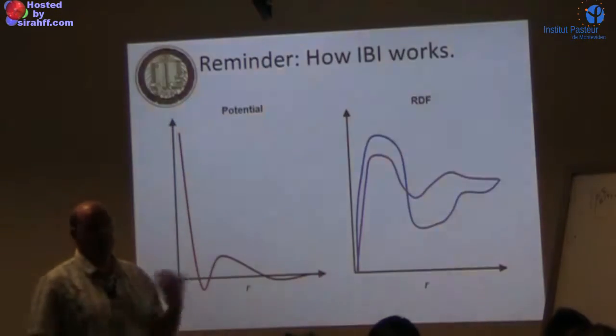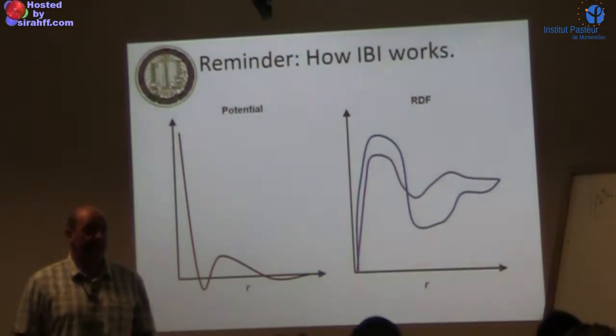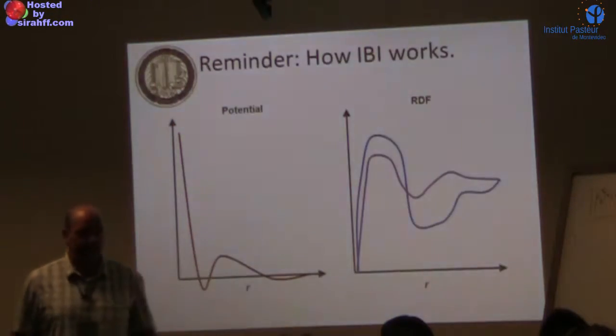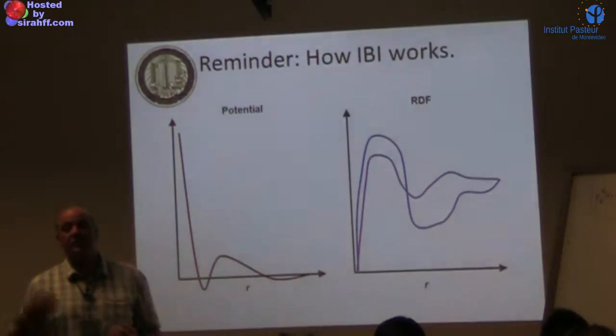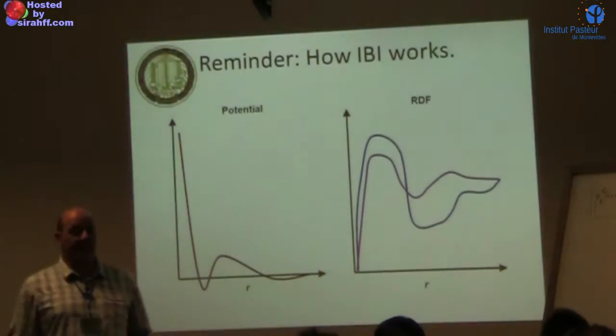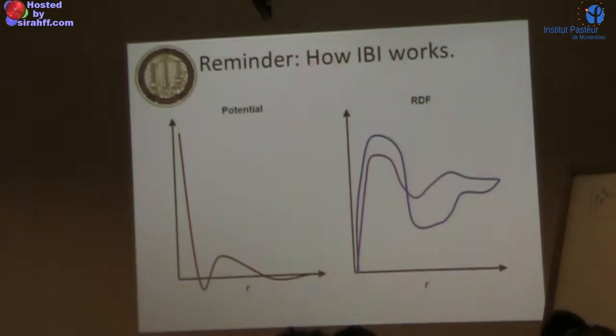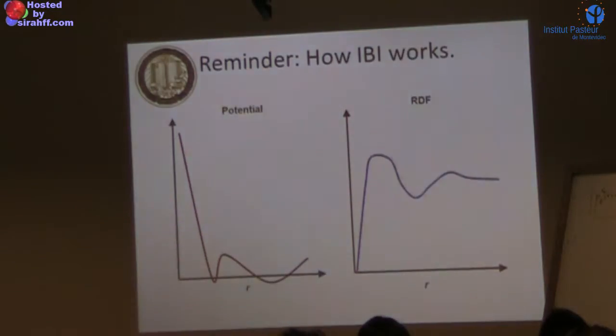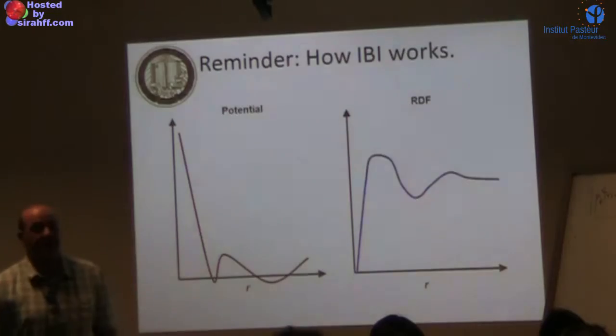As I said yesterday, it's a mixture between potential and free energies. Especially at high densities, the packing of beads becomes very important. It's been known since the early 1970s that the repulsive part of the potential dominates the local packing, whereas the attractive part dominates elsewhere. We iterate this a number of times, and after a few iterations, we normally converge, at least for homogeneous systems.